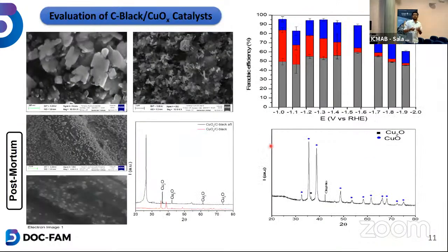So in the next step, I have used the carbon black, which is Vulcan XC72, and I just added both of them in one chamber, and then I carried out the reaction hydrothermally at 160 degrees for 12 hours, and then I have platelet-like morphologies. I don't know where they originated from, but they are platelet-like morphologies. So this is all carbon, on which it's nicely surrounded by copper. So when I tested this in the flow cell again, initially I have seen mostly copper 1 and copper 2 phases of copper here.